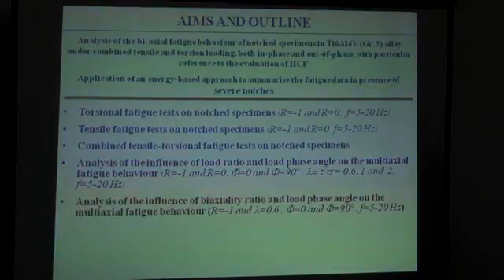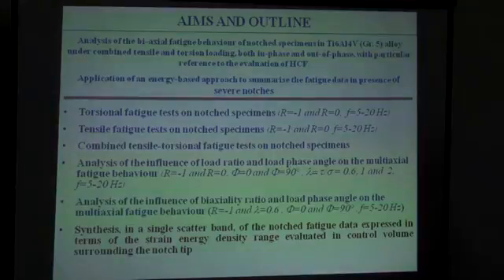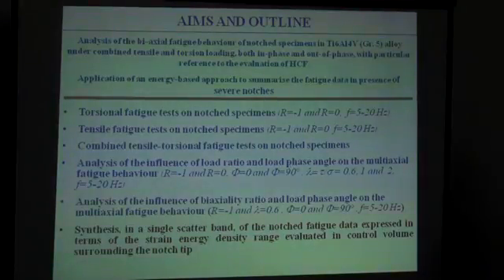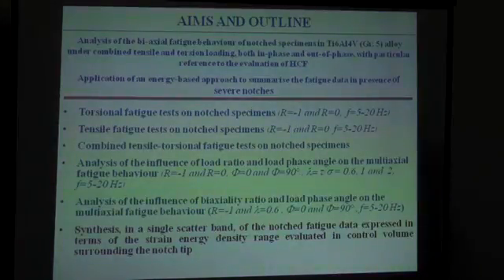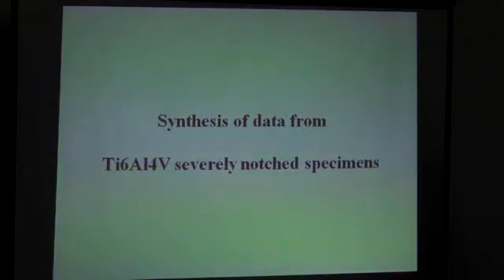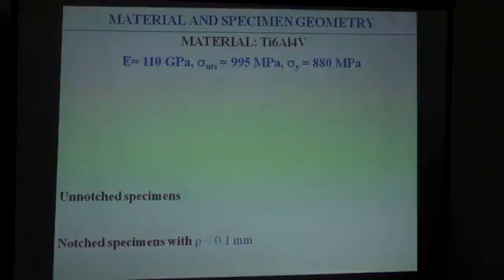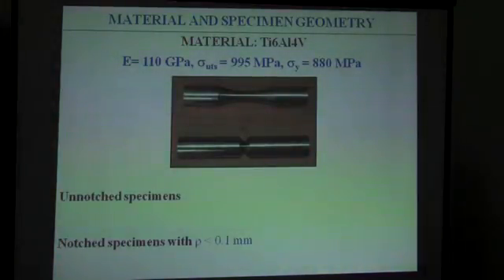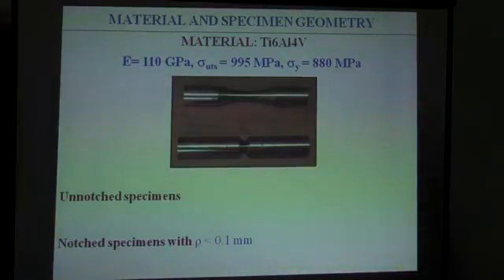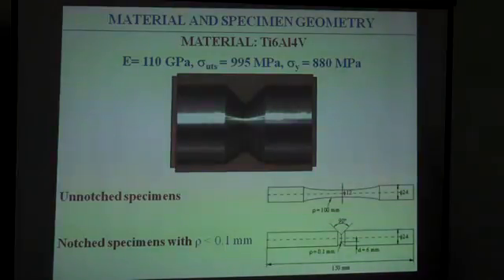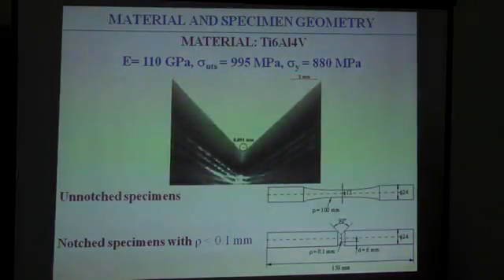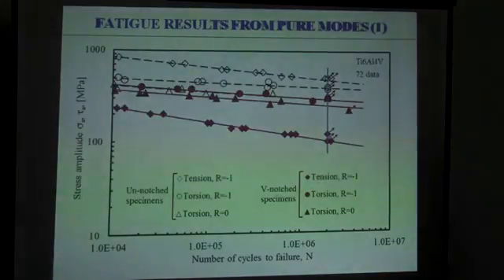Now I will show the imaging of the specimen, and we would like to show if it is possible to reach a good final synthesis by using the strain energy density. The synthesis of the data from titanium alloys is reported here. We have considered this kind of specimens, a plain specimen and a notched specimen with a notch opening angle equal to 90 degrees and a very small notch tip radius, less than 0.1 millimeter. This is an image of the notch radius. This is a typical measure of our radius.